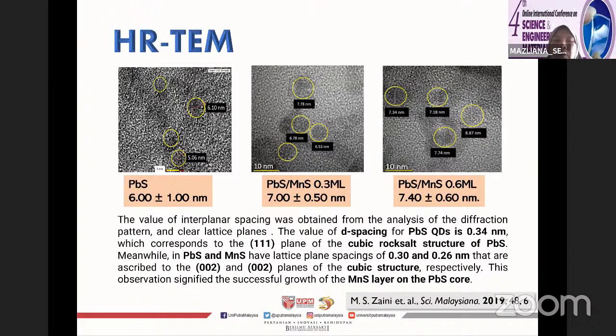To confirm the formation of the MnS shell layer, we analyzed this image using ImageJ, got the value of the plane, and compared it with the XRD data library. From the interplanar spacing, the d-spacing in PbS is 0.34 nanometer, and this corresponds to the 111 plane in PbS cubic rock salt.